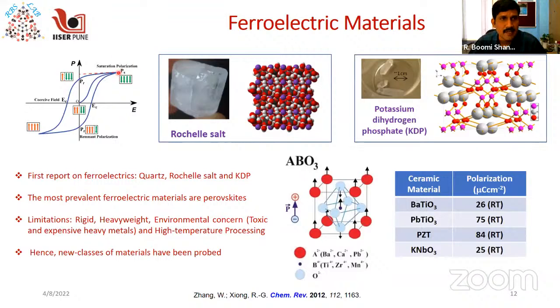In that saturation polarization, all the dipoles in the system are oriented in one direction. However, if you withdraw the electric field, not all the polarization goes back to its original state. Most of it is retained, which is called the remnant polarization. So remnant polarization is the polarization realized at zero electric field. If you then want to push the polarization in the opposite direction, you have to give an extra electric field in the opposite direction, and then the polarization gets reversed and saturated in the opposite direction, and the cycle is completed by the forward and reverse electric field applications.